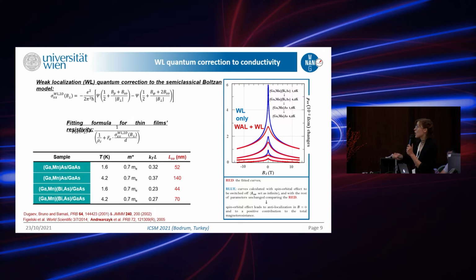As you may see, it's an equation correction to the conductivity based on the digamma function. And in the digamma function, Dugaev, Barnas, and Bruno, who are the authors, introduced something like 3 different parts of the field. So it's a field corresponding to propagation with the elastic scattering, which is B_e, inelastic, which is B_phi, and spin orbit. All of them depend on the mean free length specifically for these regimes. And the end result was for spin orbit, because that's what we're interested in.